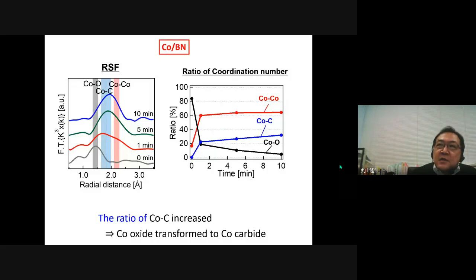So the right figure shows the variation of the ratio of coordination number. Before ethanol supply, cobalt catalysts were mainly cobalt oxide. But after nanotube growth started, cobalt catalysts became a mixture of cobalt carbide and cobalt metal. Next slide, please.